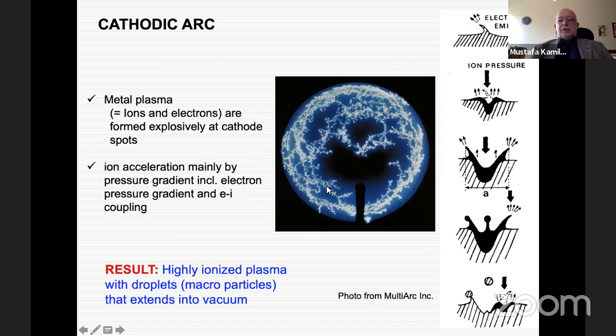So when the cathode burns, as you see, this is a very high speed camera view of a cathodic arc moving on the surface. Each cathode spot stays on one point for microseconds and then starts to travel all over the cathode surface, leading to melting and evaporation. In the meantime, because of the electrical field that is created here, we have lots of electrons, and these electrons get in contact with the metal vapor and convert it into an ionized state. So we have a very highly ionized plasma that contains almost 90–95% ionic form.